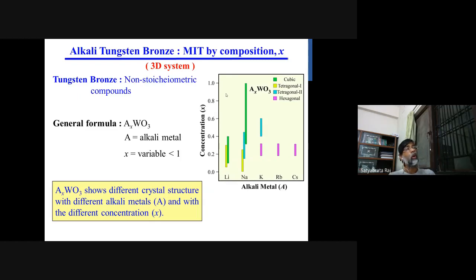So let's actually, I'll talk about the parent compound WO3, which is tungsten trioxide. Let me pick up a three-dimensional system. WO3 is a three-dimensional system, you can dope many alkali metals, if you put lithium, sodium, potassium, rubidium, cesium. With your alkali metal, the crystal structure changes, different hexagonal, then tetragonal 1, 2, then it goes to cubic. And also with a different concentration, a different structure develops with a single alkali metal.